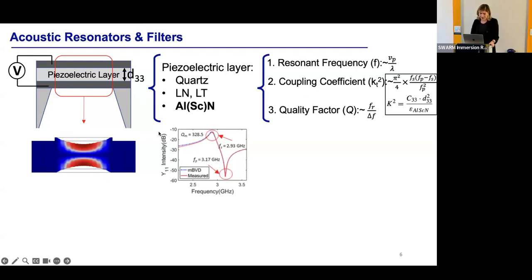So what do we care about in resonators? Here you can see a mode shape. It's a thickness extensional mode of this resonator structure. And if the frequency of the AC signal that you're applying matches the mechanical resonance frequency of the structure, you get a very sharp peak in the impedance or admittance response of your resonator. So here again, the input is electrical, the output is electrical, but the signal processing, where this resonance is happening, is in the mechanical domain, and that allows you to get higher quality factors than you normally can with electronics.